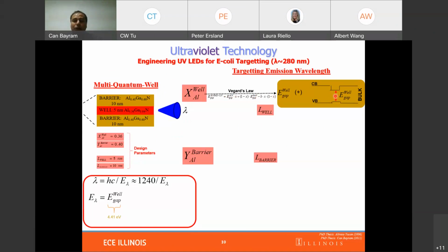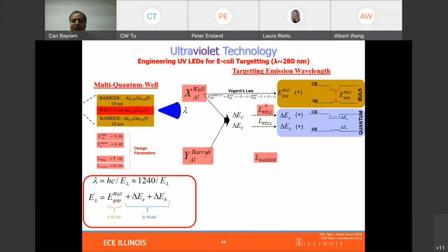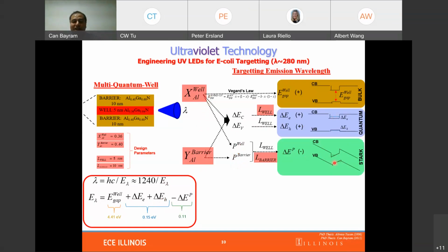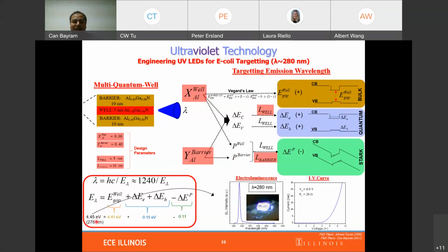Now, by just looking at the aluminum content of the well using Vegard's law, we can calculate the bulk component contribution to the emission, which is written here. By looking into the aluminum content of the well and barrier, we can calculate the band offsets, and given the length of the well, we can find the quantum contribution to the emission wavelengths. And by looking at the aluminum content of the well and barrier and considering the polarization nature of the system, we can look at the Stark effect contribution that comes in this term.